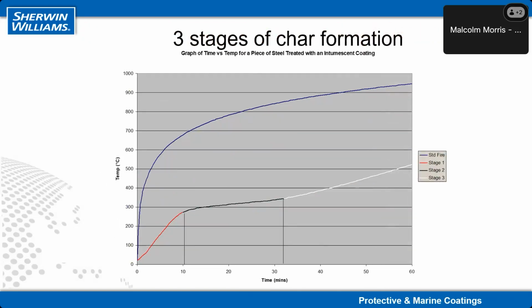There are 3 stages of intumescent char formation. The red area at the start of the graph is basically the paint system heating up according to the furnace. There's not much reaction happening until the paint reaches about 275 degrees C, and then the black line in the middle is where the curve actually flattens off a little bit. This is where the chemical reactions are taking place to form the carbon char. These chemical reactions are actually what they call endothermic. They absorb heat out of the fire, so the actual curve flattens off a little bit there because of the endothermic heat absorption effect of the chemical reaction.